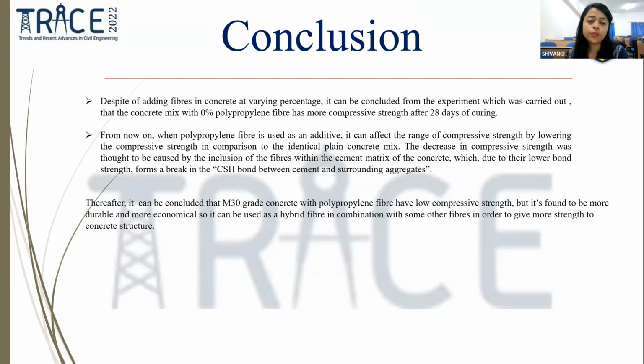From now on, when polypropylene fiber is used as an additive, it can affect the range of compressive strength by lowering the compressive strength in comparison to the identical plain concrete mix. The decrease in compressive strength was thought to be caused by the inclusion of the fibre within the cement matrix of the concrete, which, due to its lower bond strength, forms a break in the CSH bond between cement and surrounding aggregates.